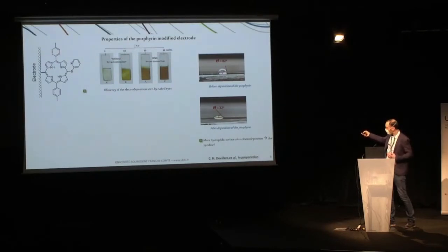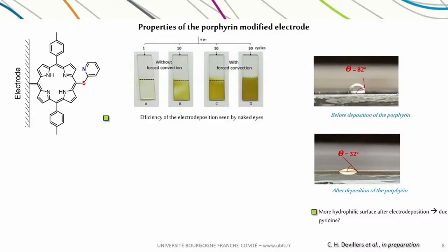lipophilic surface, so hydrophobic also, because when we add a drop of water onto the surface, we have a high contact angle. And here you can see that the water likes the surface because it is spread over the surface. And this is after deposition of the porphyrin. And that means that probably the material is much more hydrophilic. So maybe it could be due to the addition of this pyridine molecule, which can make some hydrogen bonds with